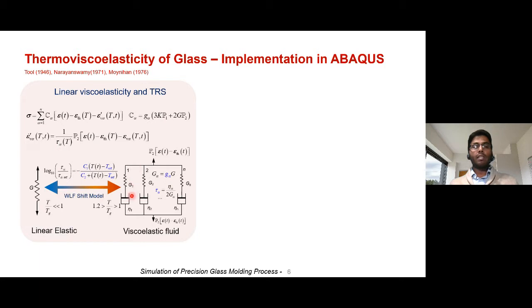I'm using a generalized Maxwell model to capture the viscoelastic behavior, and tau alpha indicates the relaxation time of each Maxwell branch. Here I'm indicating the Maxwell branch with a scalar quantity G, because only the shear components participate in the relaxation behavior. Now this is what is happening at higher temperature. The material is softened, so it behaves like a viscoelastic.